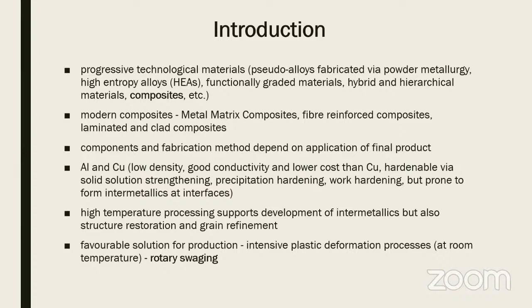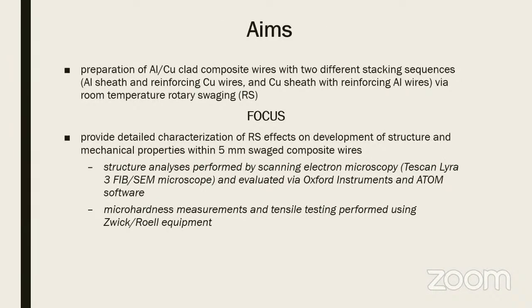So, by this reason, high temperature processing is unfavorable because of the danger of the formation of intermetallics, but we can choose some different processing at room temperature, which can advantageously be done via intensive plastic deformation. Here we have chosen the rotary swaging method. The aim of this study is to prepare clad composites via the rotary swaging method. We have chosen two different stacking sequences, we will see on the next slide. And the focus of our study was to characterize the effects of rotary swaging on the development of structure and mechanical properties within wires, which we swaged down to 5 millimeters.